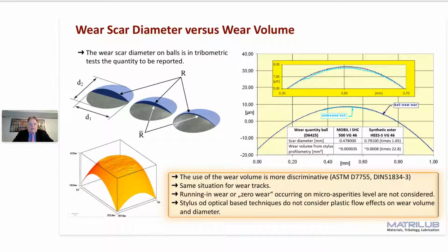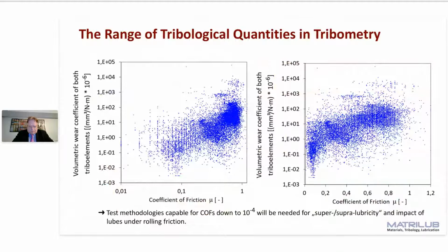And you need here other techniques which can measure the shape of microasperities before and after a test. So it is also here possible to determine wear, but on this level you have the problem: the changes in topography, were they done by plastic flow of the microasperity or really by an irreversible loss of material? So finalizing, the first takeaway here is if you only look at the wear scar diameter, it can be misleading, and one should look at the wear volume.